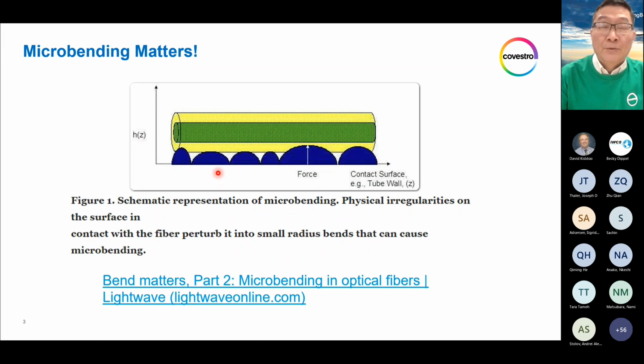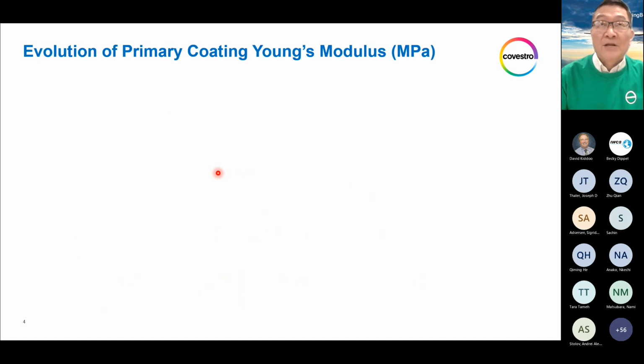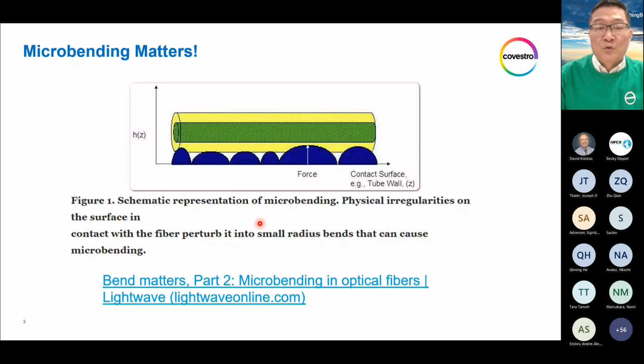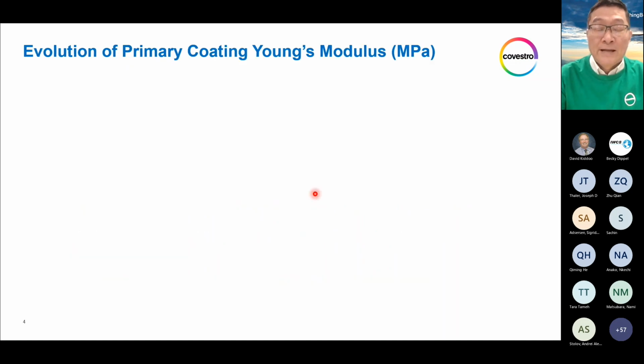Now go back to that configuration I just talked about. You have glass cladding, then you have primary coating, secondary coating. The soft primary coating serves as a cushion to absorb all the forces coming from different sources, like lateral force, so that any force that can be transmitted into the fiber is reduced. Therefore, it is natural to reduce the primary coating's Young's modulus, so that the cushioning effect becomes greater and greater for the more modern and more challenging fiber configurations in the modern days.